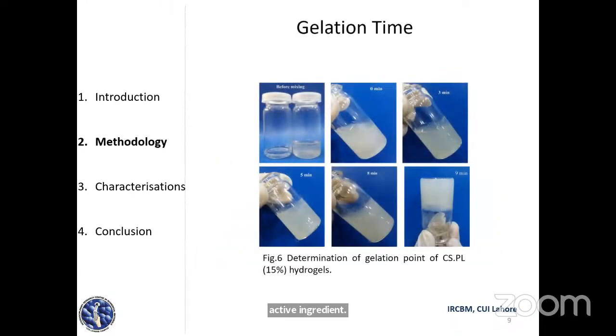Next, we have gelation time. We determined the gelation time by the inverted tube method. The hydrogel solution was shifted from 4 to 37 degrees into a glass vial. The glass vial was tilted after every minute, and the flow of the hydrogel was observed with the naked eye. The gelation time was noted when the hydrogel stopped flowing. And in this hydrogel formation,